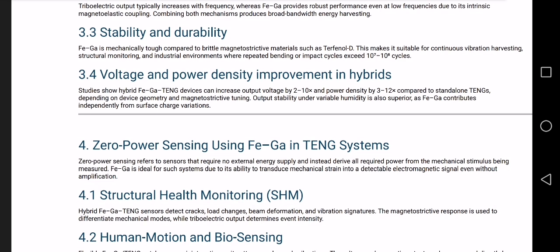Voltage and power enhancement. Experimental studies show voltage increases by 2 to 10 times. Power density increases by 3 to 12 times compared to standalone TENGs. Also, output is more stable under humidity changes.